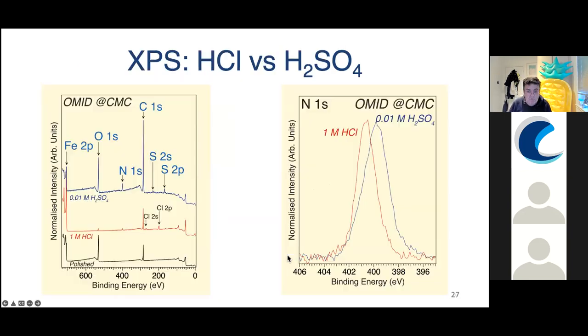So I've just shown this cartoon here. We know what happens with 1 molar hydrochloric acid with OMID at CMC. We have the molecules adsorbing on metallic iron in the presence of these adsorbed chlorine atoms in these two singly protonated states. What we want to find out is, is the same going on in sulfuric acid or is something different? So let's look at the overview spectra first. So here I'm showing a polished sample, as shown before, the 1 molar hydrochloric acid with OMID at CMC, and then in 0.01 molar sulfuric acid with OMID at CMC. And you can see the spectra look different.